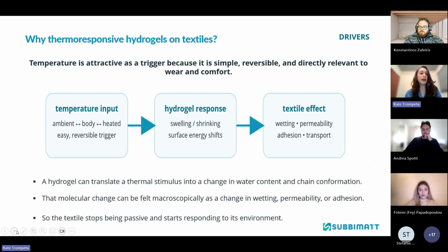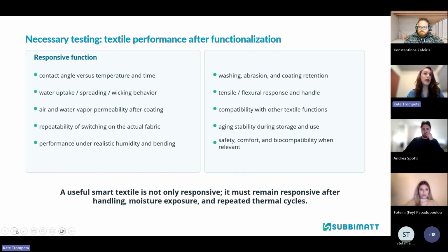So to take, for example, the heat from our body, which is an easy and reversible trigger. The hydrogel can respond, so it can swell or shrink, and also have some surface energy shifts. With this, we have an effect on the textile, and this changes its wetting, its permeability, its adhesion, or the transport of air and humidity through its pores.